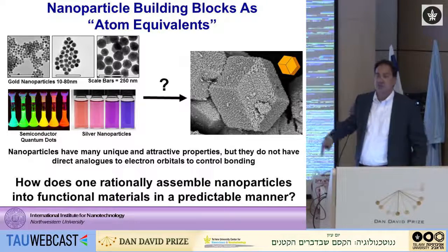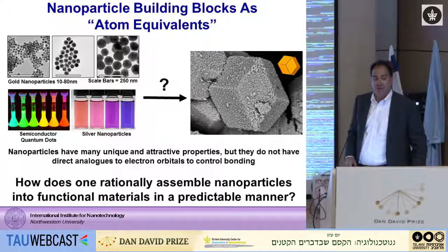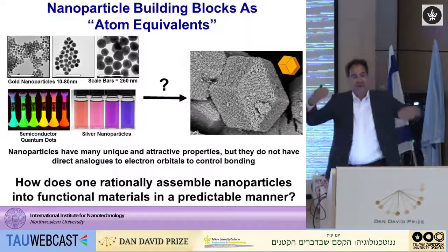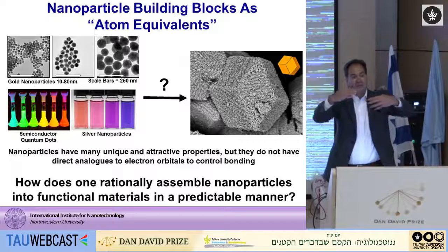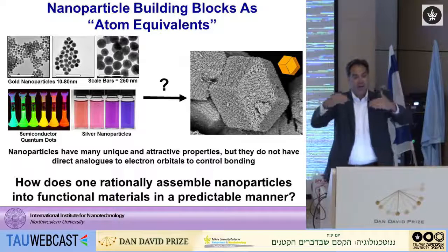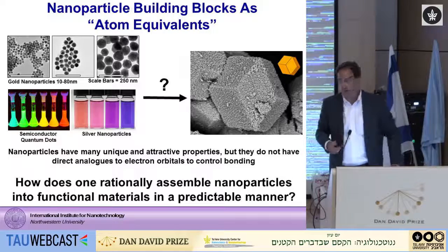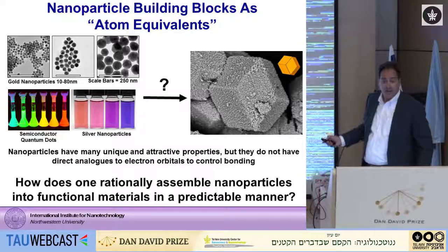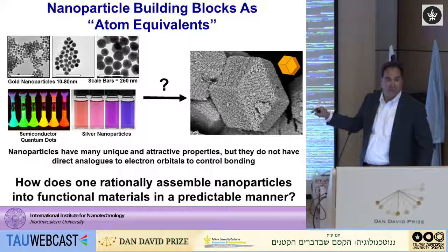We were stuck in kinetic traps, as I'm going to show you, in the 90s. We'd used long linkers, and so the system had not equilibrated and come to the final thermodynamic product. This is a BCC crystal structure. It's a rhombic dodecahedron. You will always get this particular structure, because this is what's called the Wulff construction. It is the thermodynamic sink.